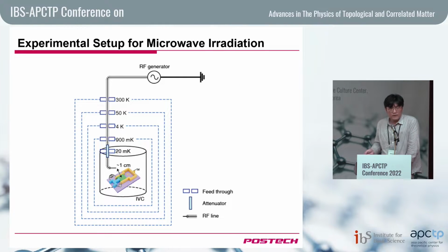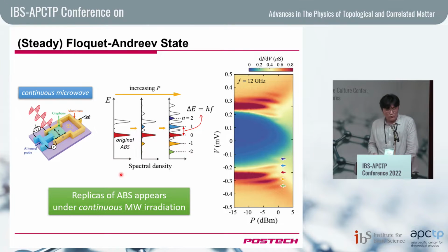Okay, then we shine the microwave. We shine the light, because this is in the gigahertz range. We used a coaxial cable like the one you use for TV, right? The coaxial cable is fitted into the fridge, minimizing the thermal load from room temperature. And we just put the center pin of the coaxial cable nearby the sample, like 1 centimeter away. This is a very poor antenna, but as far as it works as an antenna, we were okay at that time. So this is our way to shine the microwave. Obviously, the microwave will not be polarized. So you can think the microwave is unpolarized for now, but with a well-defined frequency and also an amplitude.